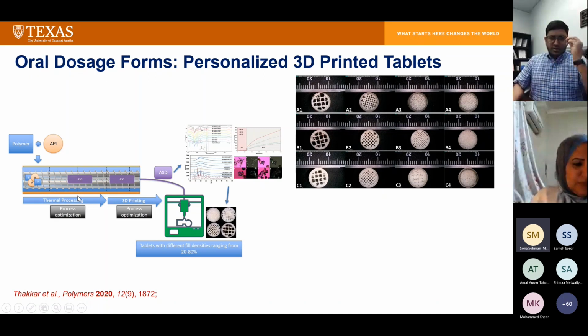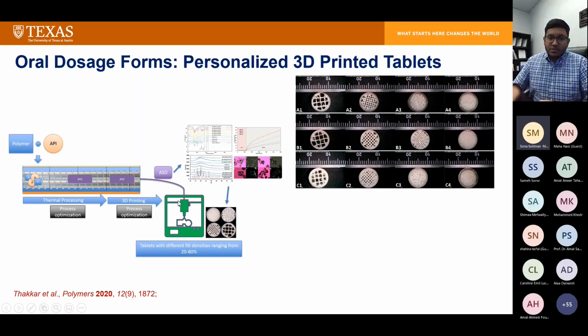So we combined hot melt extrusion with an FDM printing based concept. We used hot melt extrusion to produce thermoplastic polymeric filaments containing drug in a solid dispersion form. And then we used that feedstock material through the fused deposition modeling based printing to produce the tablets of interest. So our target was to produce various tablets with different kinds of porosities.